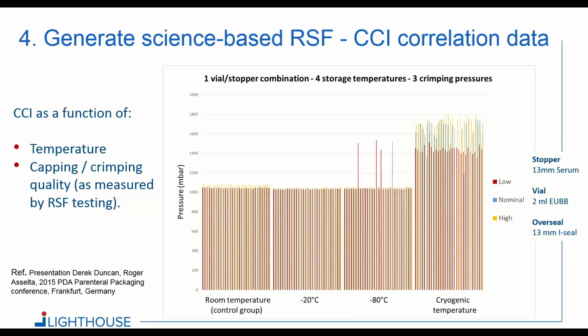And again, here we're using yet another headspace measurement as the CCI indicator. So here we're looking for that overpressure phenomena that you can get. This is data from one vial stopper combination, but 4 storage temperatures. And you see a room temperature control there. You see -20, so frozen, but -20. Frozen -80, so that's below the TG of the rubber stopper, and then cryo on the very right.